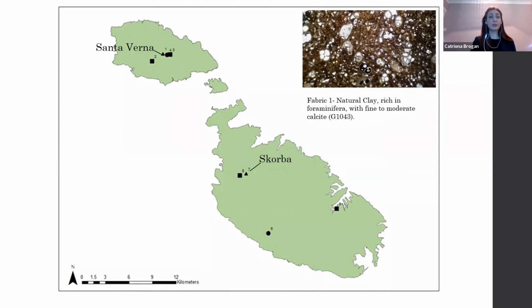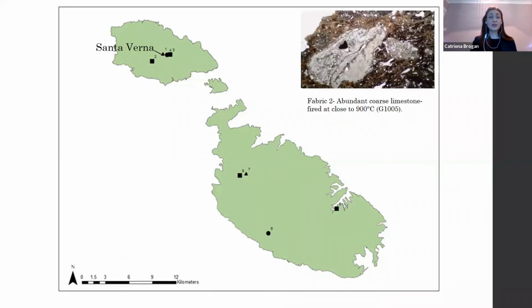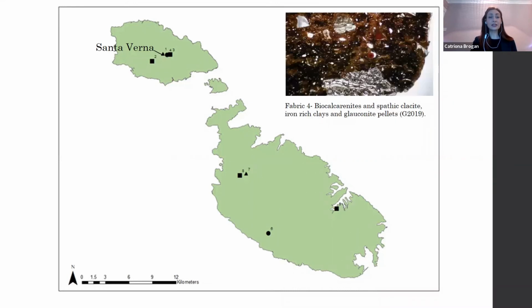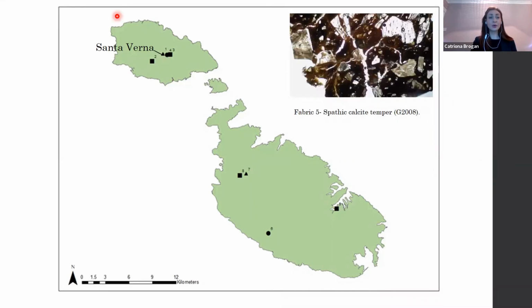And then just to quickly take you through the fabrics and where they occurred, fabric 1 occurred on both islands, so it appeared in Santa Verna and Skorba. Then fabrics 2, 3, 4 and 5 were all found on Gozo. Just a slight caveat for these: we had a limited number of sites sampled and a limited number of sherds sampled, so this isn't really indicative of their actual spread across the whole islands, but for now it just gives us a rough idea of the general areas in which we can say they were found.